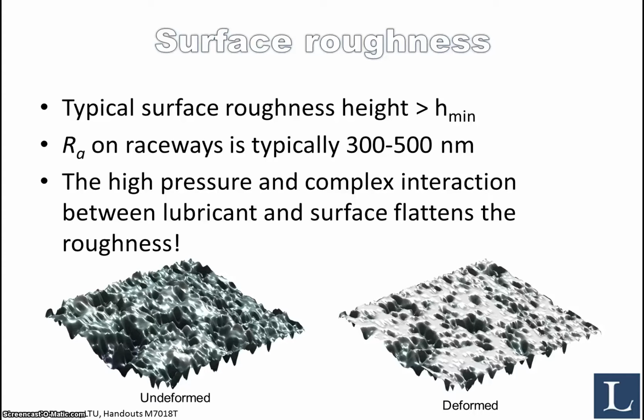For instance, indicated here in the second bullet, the Ra value, the average surface roughness of the raceway, is typically in the range 300 to 500 nanometers. But due to the high pressure that we get from the small contact area and the load acting on the rolling element versus the race, and the complex interaction between the lubricant and the surface, that will actually flatten out the roughness and enable the film buildup and separation of the surfaces.